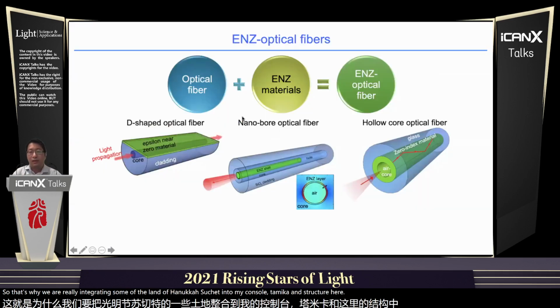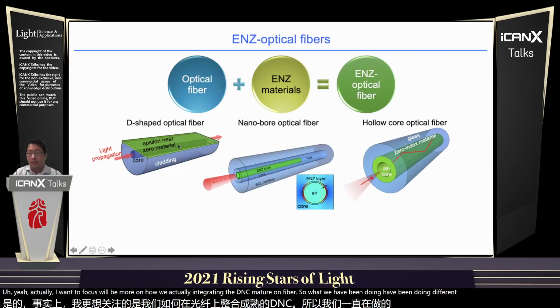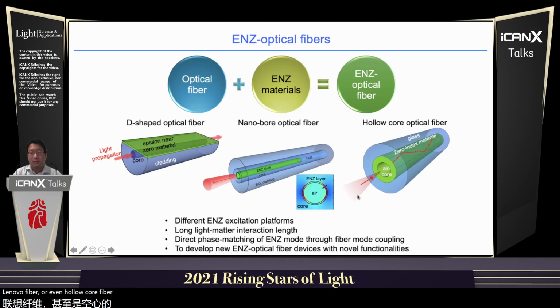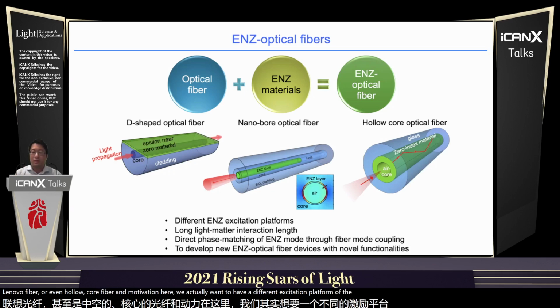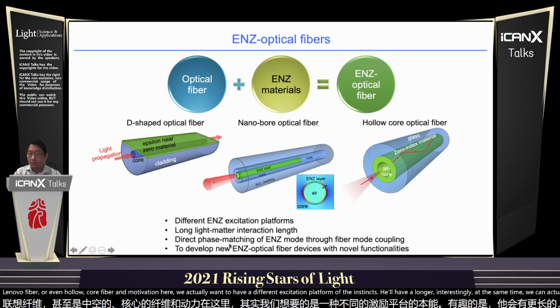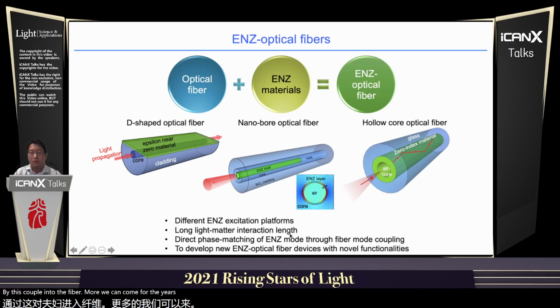But here I want to focus a little more on how we are integrating the ENZ material on fiber. We have been working on different platforms: D-shaped fiber, nanobore fiber, or even hollow core fiber. The motivation is that we want a different excitation platform for the ENZ material, with a longer interaction length. At the same time, we can have automatic phase matching. By just coupling to the fiber mode, we can couple to the ENZ mode automatically without any preset. As a result, we can also potentially make devices with novel functionality in fiber.